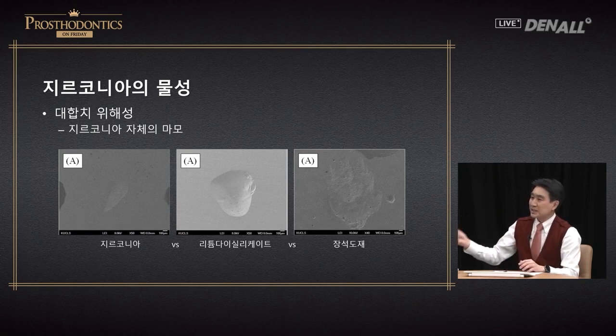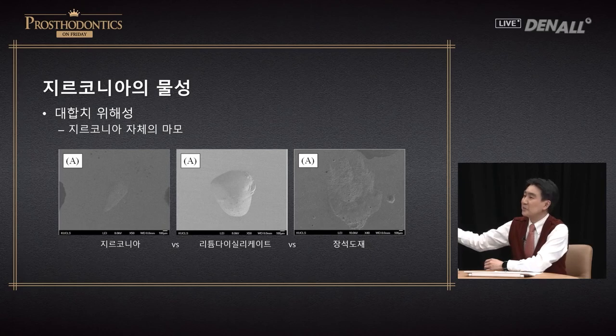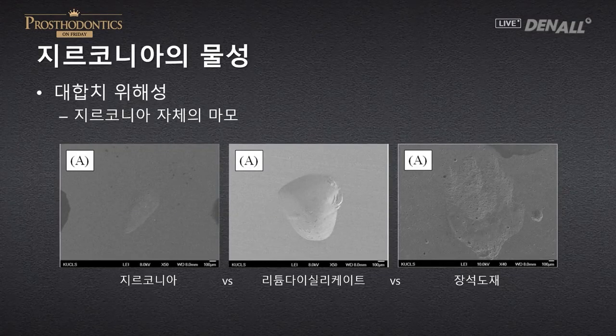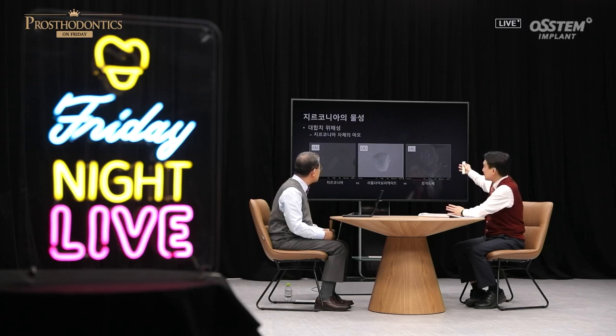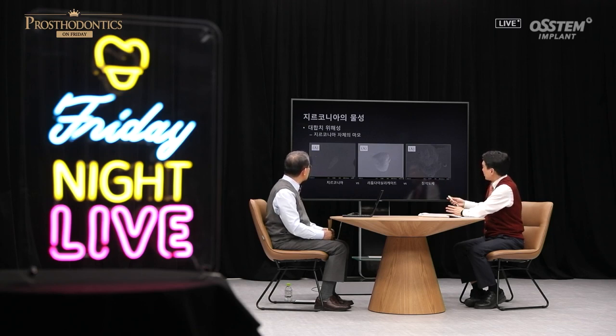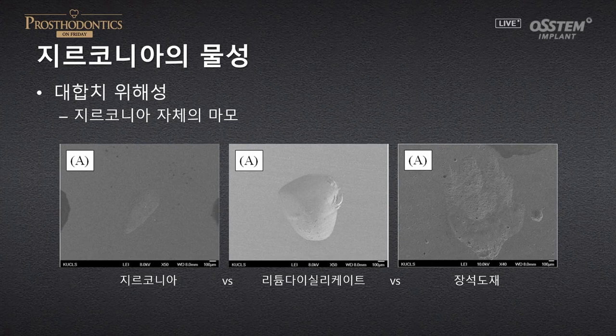This is wear on zirconia after having caused a wear on natural tooth, and this is looked at via microscope. In zirconia, you cannot really see the dent. There's barely a mark. In the case of lithium disilicate, e.max Press, you can see a small dent. On the far right is the feldspar ceramic. It doesn't look deep, but the scope is extensive, and it's quite deep too. It looks very roughly chipped off. You can see that the material of prosthesis, which is in contact with natural teeth, also goes through wear.